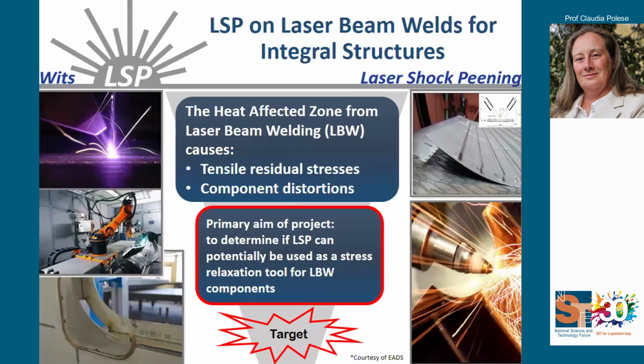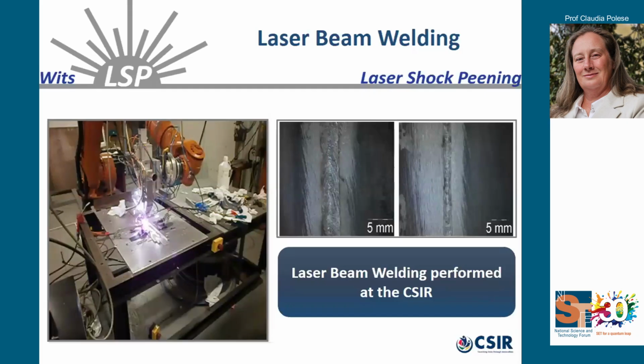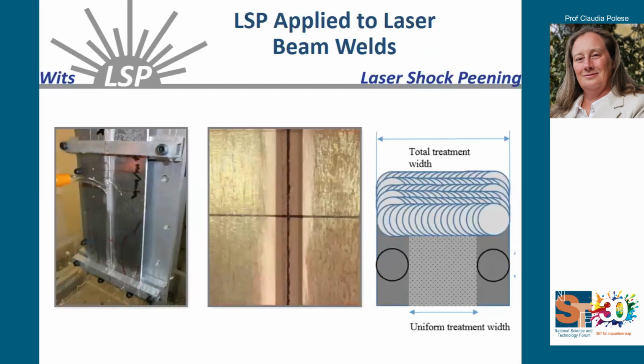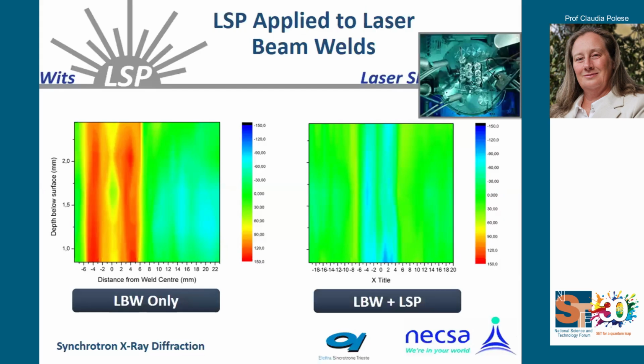You see, this is another laser technology, one of those approved in the Aeronautical Centre to create what we call an integral structure. Instead of having different components joined or riveted together, we weld them directly with the laser. Unfortunately, this leaves behind some distortion and residual stress, which is going to shorten the life of the component. The idea was, can we target laser shock peening on the surface of these joints and see what happens? We have a laser beam welding facility at the CSIR. We put some laser shock peening on top of this, in a fashion similar to the process I showed you before, and what we achieve is a complete reversal of the tensile residual stress, a relaxation of all the distortion that we have here.